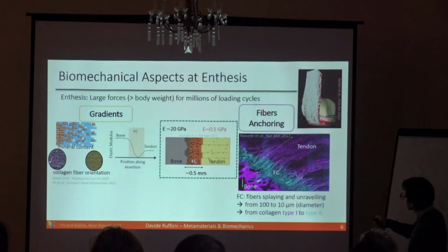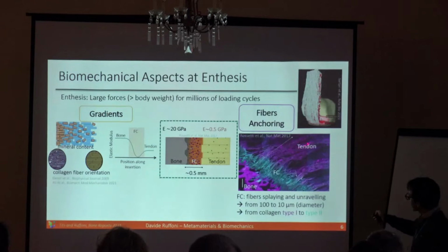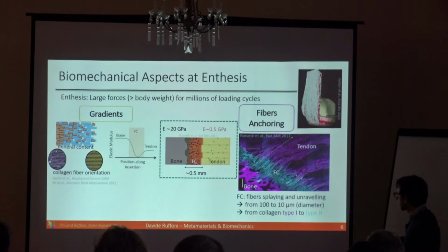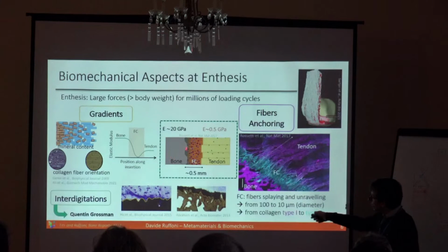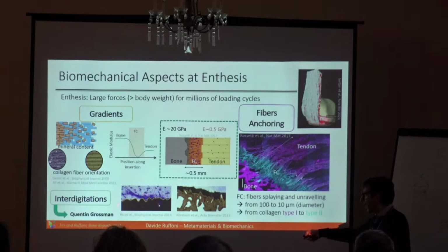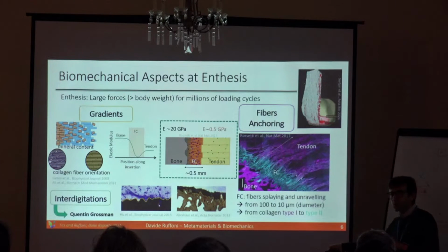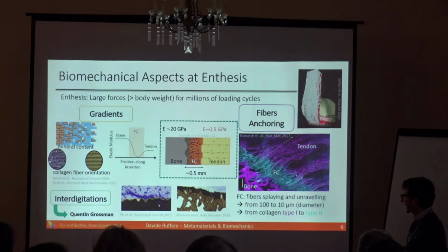Then what is also quite interesting is that those tissues are fibrous tissues, and what people have discovered is that tendon fibers, which are depicted here in purple, before attaching to bone, splay out to increase the attachment area, and they also unravel into smaller fibrils. So this is something that has been investigated. And last but not least, those interfaces between tendon and fibrocartilage and between fibrocartilage and bone are not flat, but highly rough and highly interdigitated. And this is also something that Quentin, my student, will show you today, in half an hour or something like this.